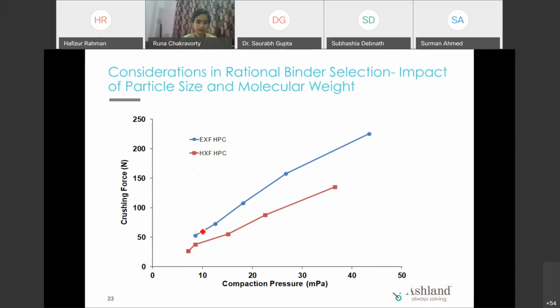Then we checked the tablet hardness at the different compression forces. We observed that the tablet in blue color, with Klucel EXF, was harder and stronger at all the compression forces when compared with the tablet containing the high viscosity, high molecular weight grade, HXF. So with this study, we can understand that lower viscosity or lower molecular weight grades give you better hardness. That's why EXF and LXF are the most recommended binders for tablets.